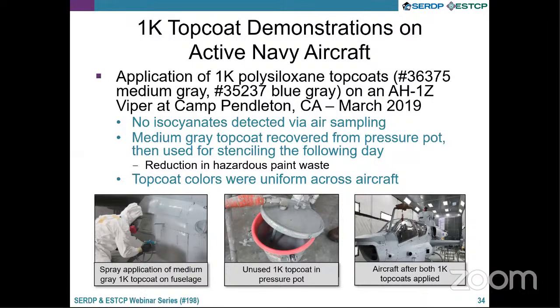A third point is that because it's a single component system, artisans noted you don't see nonuniformity across the aircraft. With smaller aircraft using two component systems mixed at, say, a 4-to-1 ratio by volume, one applicator might mix it perfectly while another mixes at 3.9 to 1, and that small pigment change can be seen by trained artisans. You don't have that issue with a single component system because everything is produced in the same vat at the factory, so it's a homogeneous color across the asset.